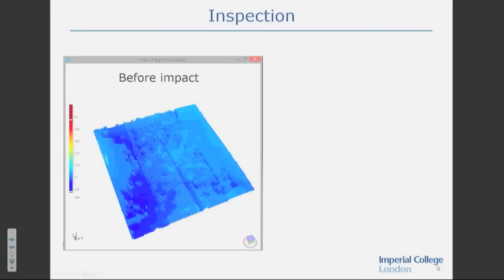And what did it show for this plate? Well, this is before the impact. We've got a depth scale here running from 0 up to 2.4 millimeters. It's nearly all in the blue region here, showing it's about 2 millimeters thick, which is good because that is the thickness of this plate.